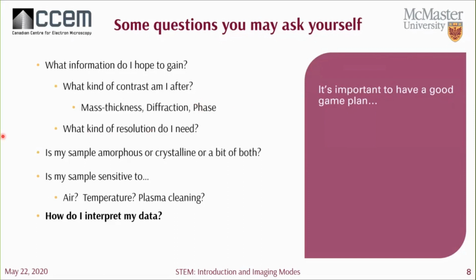From this, you can ask yourself, what kind of contrast am I after? Am I after mass thickness contrast, diffraction, or phase contrast? And also, what kind of resolution do I need? In some cases, obtaining really high resolution requires special sample preparation, which could be quite costly in that we might need to make a uniform thin sample using the FIB. That would increase the time standing between you and some really, really nice data.